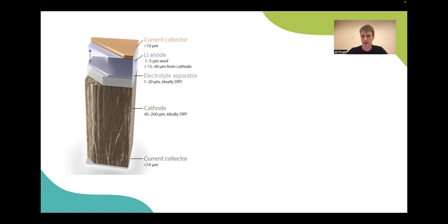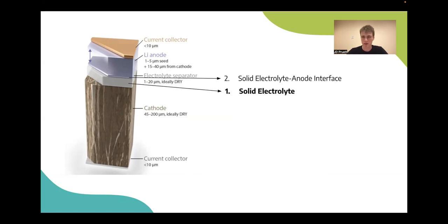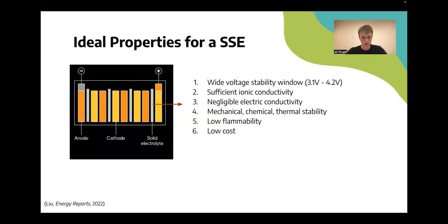So there are two areas that I want to touch on regarding challenges. The first being picking the solid electrolyte, and the second being what happens at that electrolyte anode interface. Let's start with the solid electrolyte. So there's a long list of properties that we would want in a solid-state electrolyte. The first and potentially most important is what's called a wide voltage stability window. In other words, this is the voltage at which a battery can run, in which the electrolyte neither reduces nor oxidizes. In a typical electric vehicle, as of today, that runs at about 3 to 4 volts.